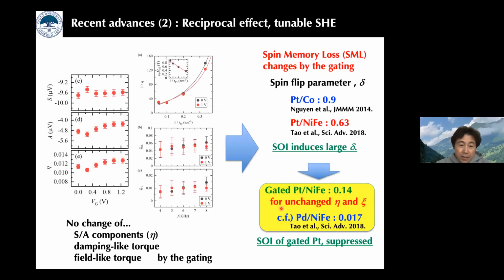More importantly, the tunable spin orbital interaction in platinum allows the suppression of the spin memory loss. Spin memory loss is attributed to the spin orbital interaction in the system. And as you see, the spin flip parameter due to the spin memory loss is quite large in combinations of heavy metals. For instance, in the platinum permalloy system, which we have also introduced, the spin memory loss ratio, the spin flip parameter, is quite large. However, by applying the gate voltages, the spin flip parameter in our platinum permalloy film is suppressed down to 0.14, almost 1/4. This is also strong evidence that the spin-orbit interaction of platinum is controlled by the gating.